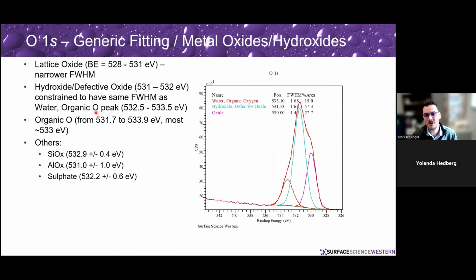If we look at a generic fitting of a metal oxide, hydroxide, I usually have a lattice oxide, which is generally a little narrower than the hydroxides and other organic components. I usually fit this peak and this peak and constrain them to have the same full width half max. That generally works out very well. But again, in a system like this, you also have to say, okay, I have these species, but what else might be present?